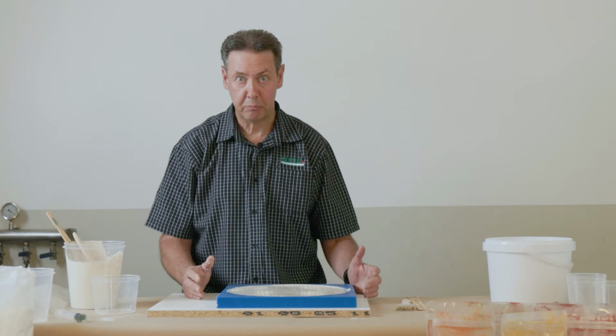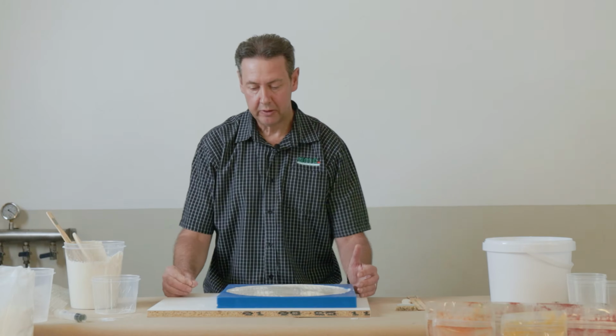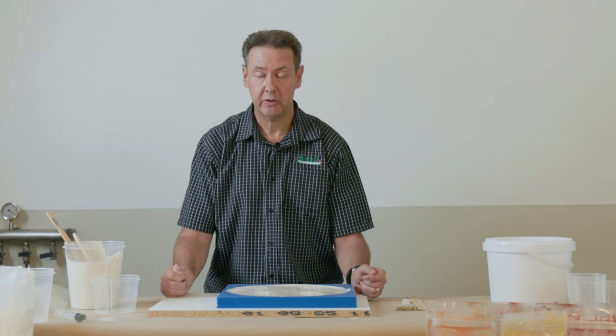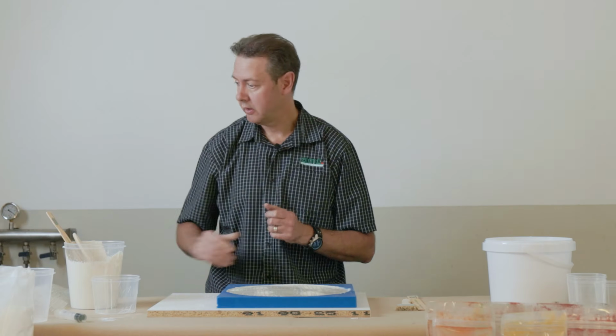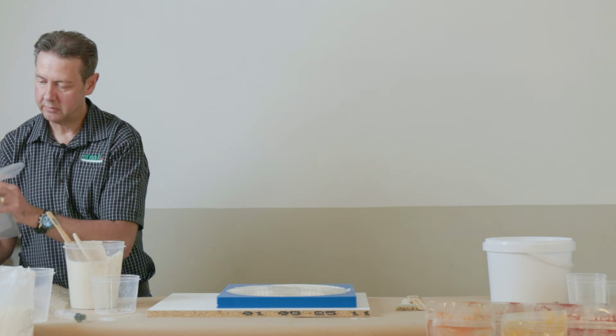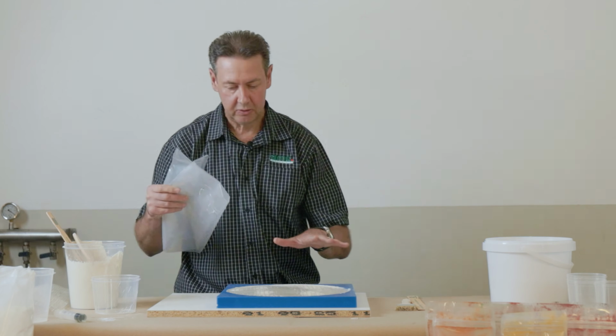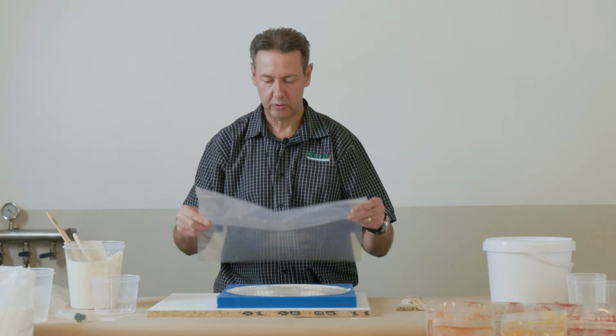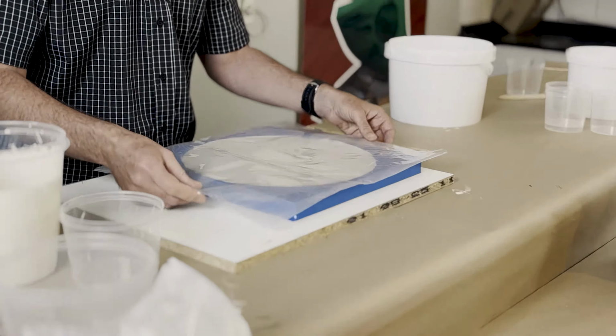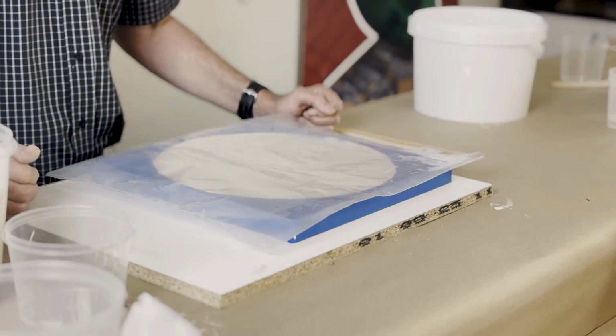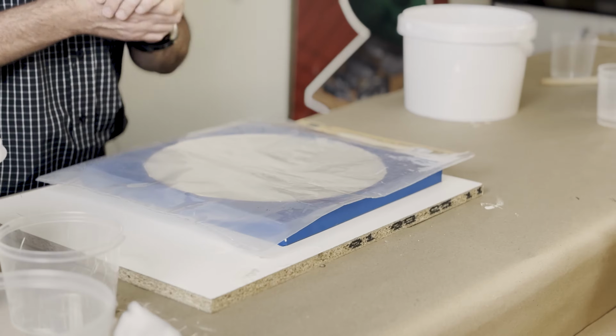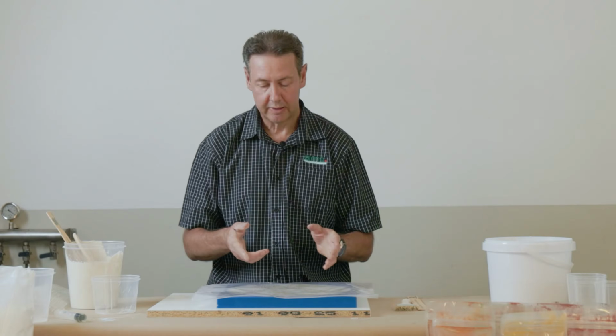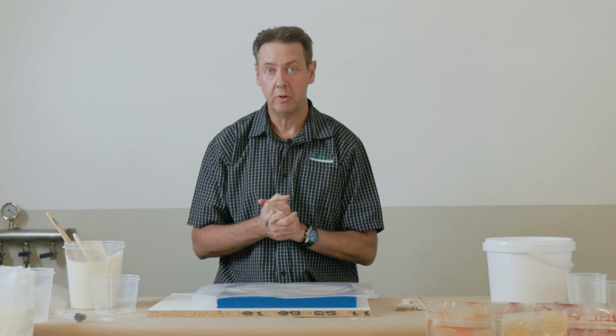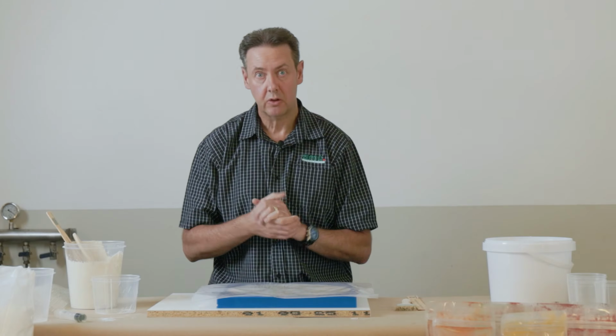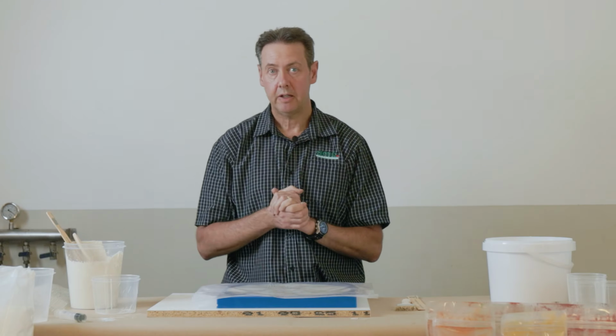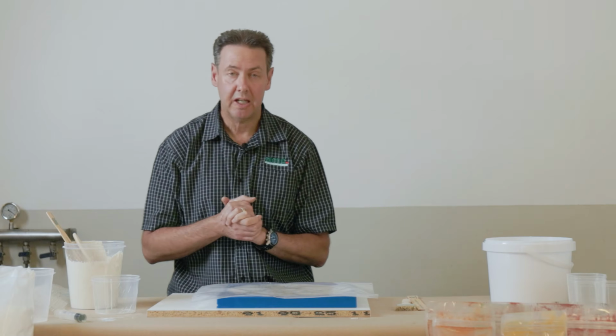So there's still a couple of important things at this stage. The one is that we don't want this to actually dry too quickly. We want it to hydrate and for the resin to cure. So very important at this stage. You could leave it for maybe 15, 20 minutes to firm up a little bit, but very important is to actually keep the piece wrapped in plastic, and that plastic will keep it hydrated. And it's best to keep it hydrated like this for probably about 16 to 24 hours. And then at that stage, you can demold out of the silicone mold. And then it's also very important for about a day to air dry this piece.